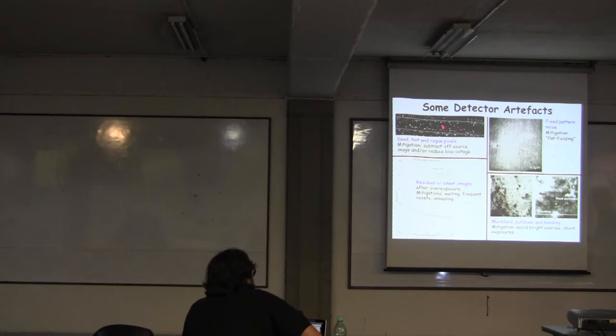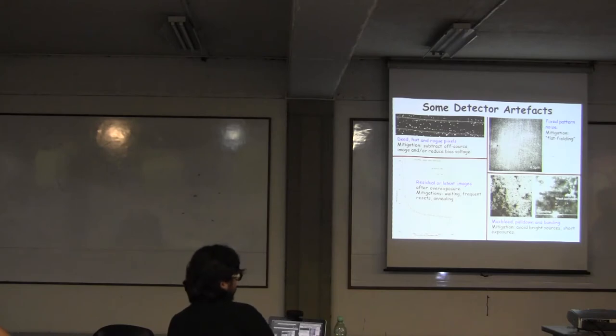Now, why are these noisy pixels there? Well, remember, the space telescope is in outer space. There are a lot of cosmic rays, and the detector is constantly bombarded by high-energy protons. And when these high-energy protons see this nice silicon crystal, they have a lot of energy. They have the power to destroy this nice crystal, to just make a defect in the crystal lattice. Then it's not our nice diamond lattice anymore, but something with a defect.